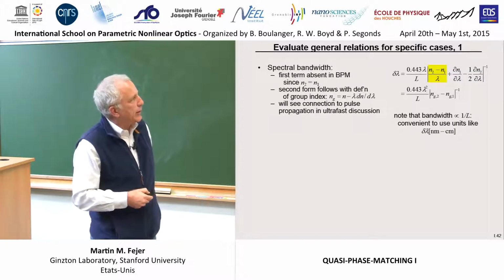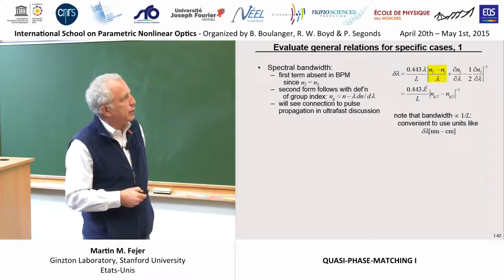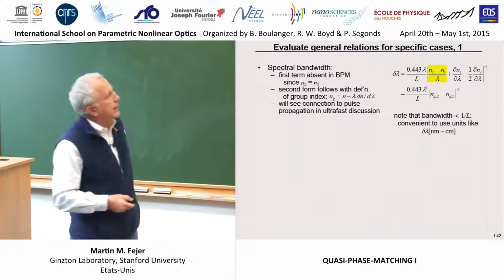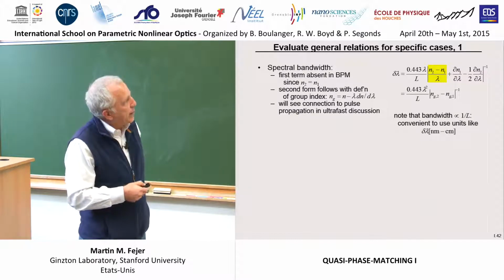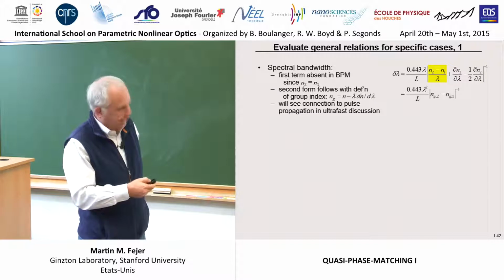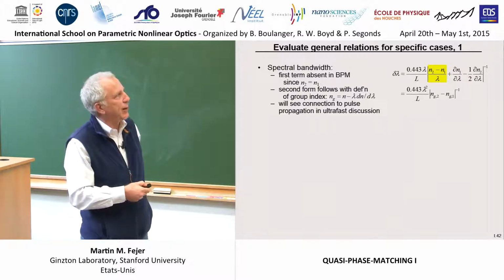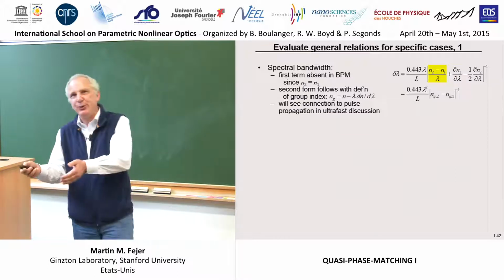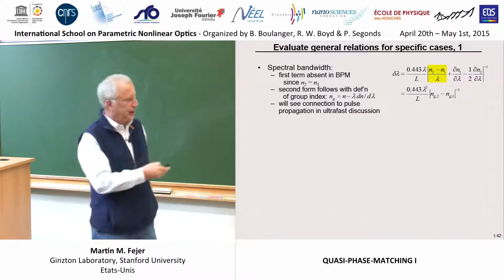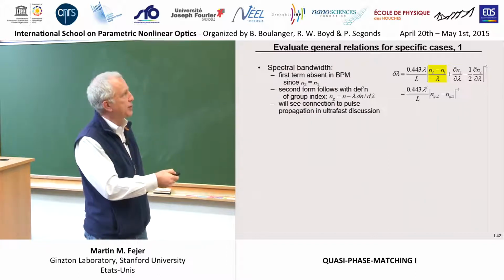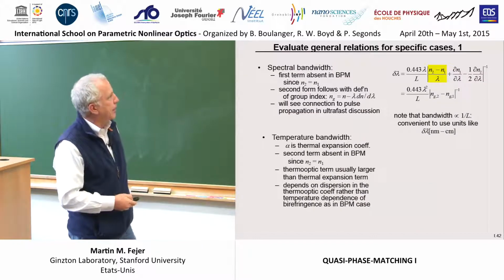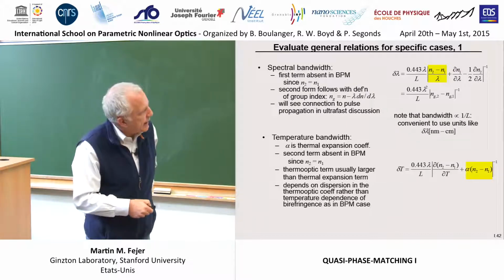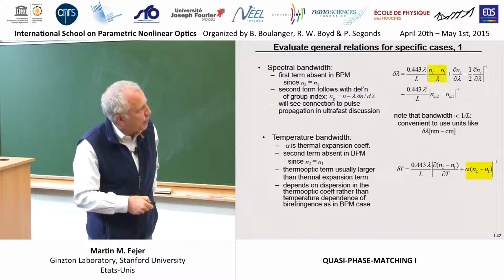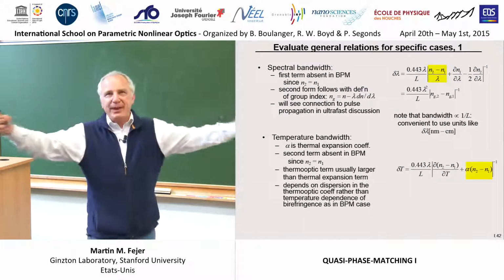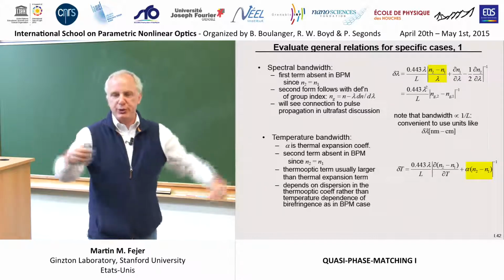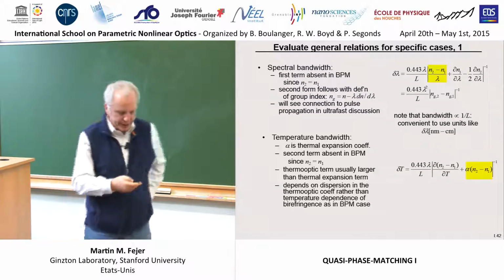And another way to look at it is you're depending on the difference in group indices, group velocities, in both cases, but in the birefringently phase-matched case, the phase velocities are matched, and it's only these derivatives that lead to some difference. But in the QPM case, even the phase velocities are mismatched. Okay. Temperature bandwidth, the same kind of story. Now the point is the thermal expansion coefficient changes the length of your grating. And so that comes into how the system will temperature tune. So you need to include this bit in your calculation if you're going to do that.